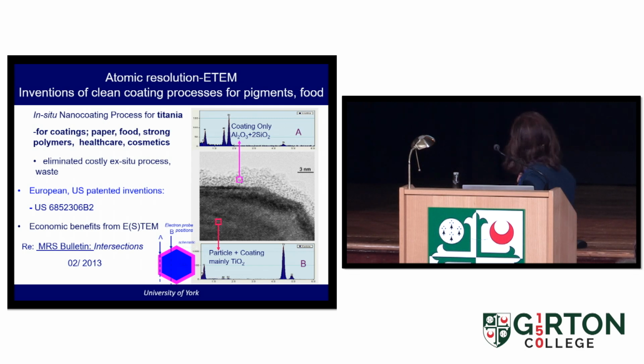at one temperature. And this shows part of that. You can see coating of alumina and silica. We can get chemical analysis to confirm that. And TiO2 is in the middle. This is the titanium peak here. So it is now commercialized. It's called R350 pigment. It's used worldwide, because everybody's house, cars, etc. depends on this painting. So on this TiO2, it's used worldwide, and it's brought a lot of economic benefits around the world. And this was our patent, and it's commercialized now.